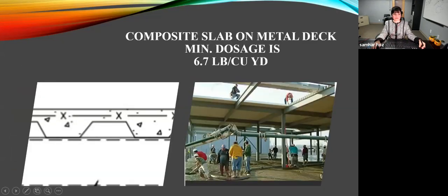Composite slab and metal decks: Helix has been used a lot in those. Minimum dosage is 6.7 pounds per cubic yard. For composite metal deck, the steel deck performs as the tension reinforcement, and then the concrete will be in compression. So that's how Helix replaces the mesh in it.